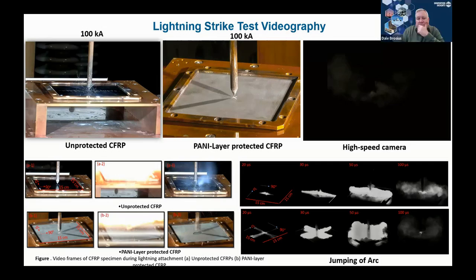Okay. But in terms of performance, I don't think it can match, or I would not yet be confident to replace the metal mesh with the coating itself. But it is on the right path. If I keep working on this and we can get more data out of it, I think there's good potential to use it in eVTOLs or unmanned aircraft, let's say. Okay, and in terms of grams per square meter, how much mass does it add? It's a good question. I tried to match the same. The copper mesh or metal mesh usually ranges from 100 to 350 GSM on the aircraft, depending on the location. The coating I showed you was 350 GSM.